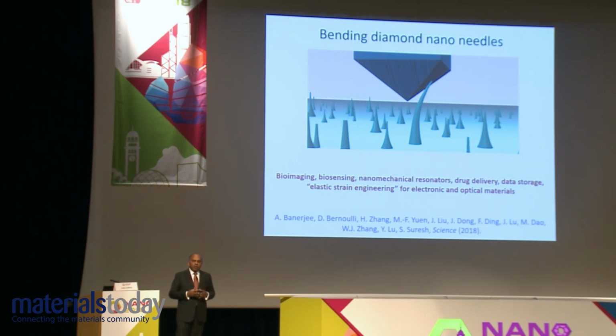There is the potential for nonlinear elastic deformation. With the computational tools at our disposal, such as the finite element method, where we can model elasticity reasonably accurately, we first experimentally show how we can deform diamond, and try to interpret through analysis what the maximum strains are. And using these, we try to understand the mechanisms. Now, why would we even expect or hypothesize that there is the likelihood of large elastic deformation in diamond? First of all, at the nanoscale, if you can create pure surfaces, the possibility of defects in diamond is relatively small. In single crystals and in very small volumes, the possibility of creating smooth surfaces and defect-free materials is large. So maybe there is an opportunity at the nanoscale that we are able to deform diamond.